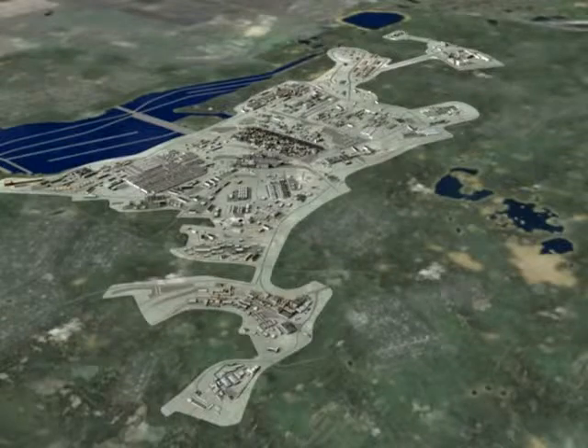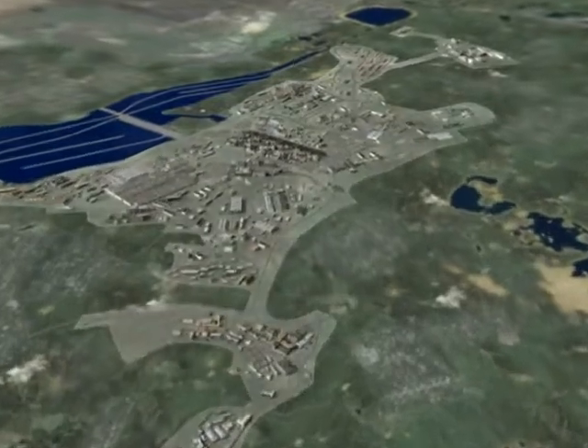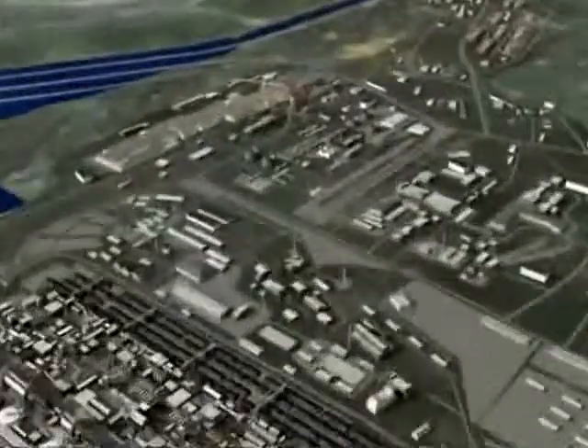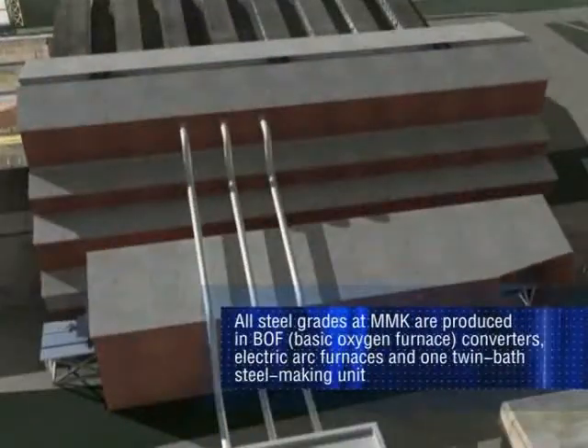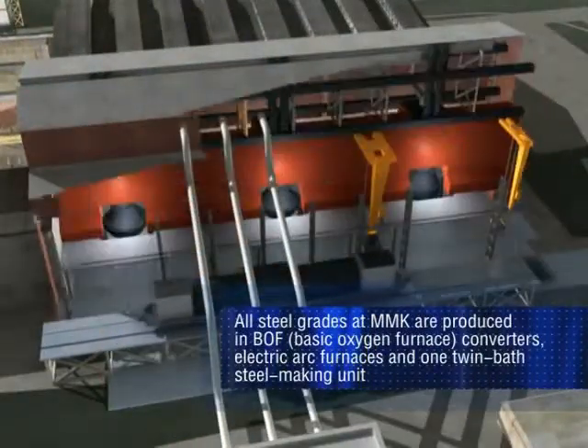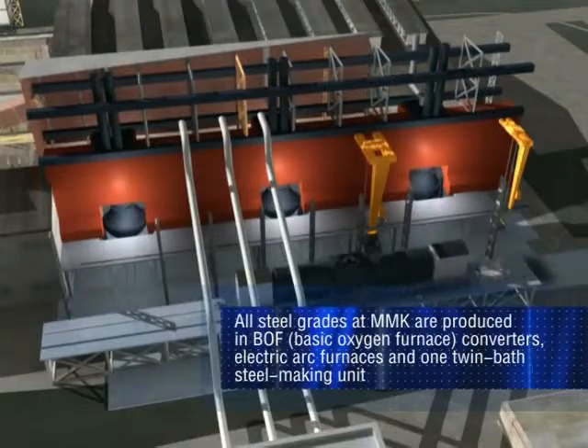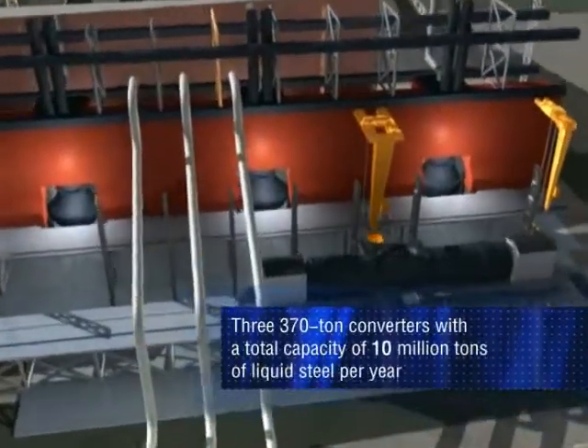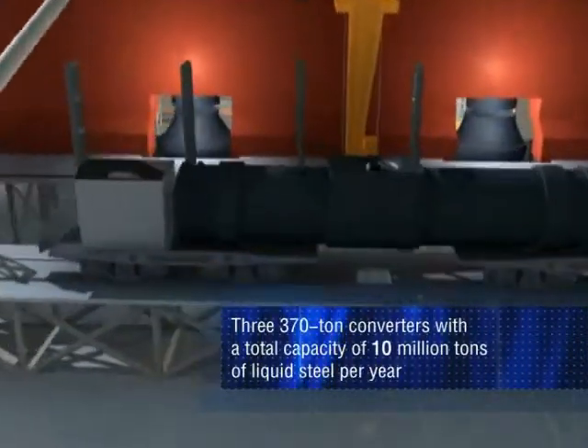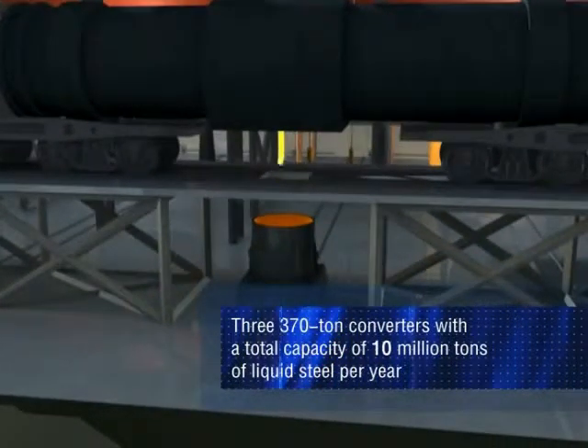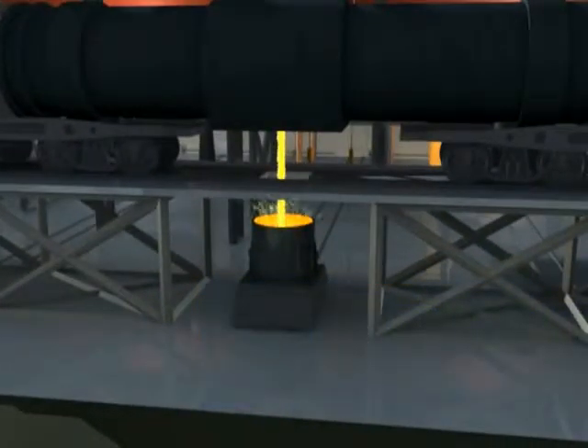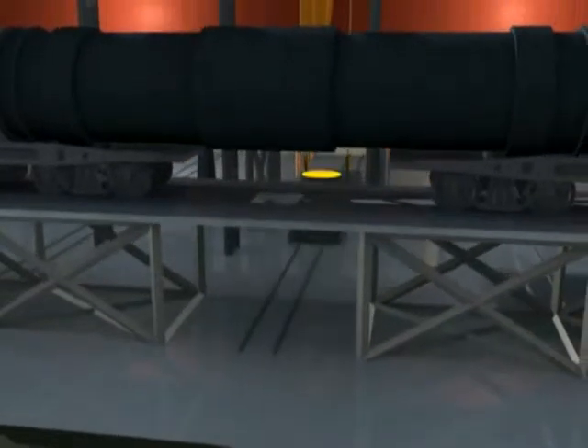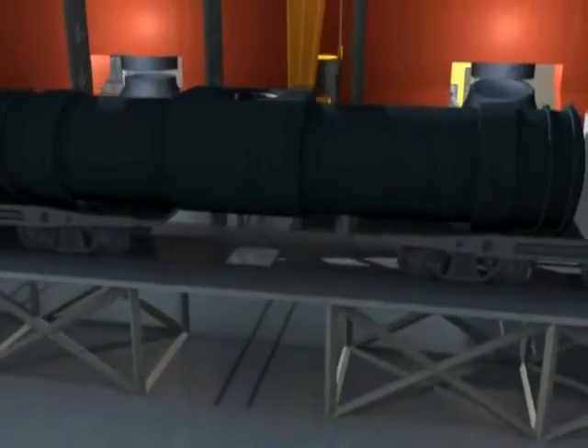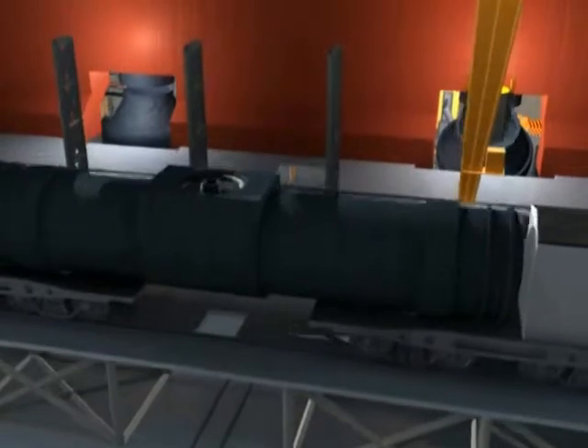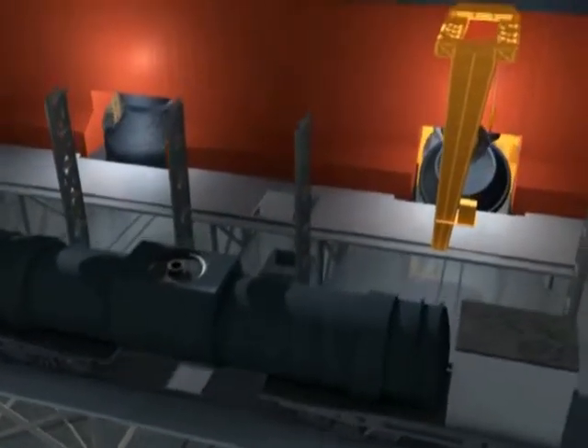All steel grades at MMK are produced in BOF, basic oxygen furnace converters, electric arc furnaces, and 1 twin-bath steelmaking unit. The BOF plant comprises 3 370-ton converters, with a total capacity of 10 million tons of liquid steel per year. Hot metal from the blast furnaces is transported to the BOF plant in torpedo cars. Then it is poured into charging ladles, and from there into the converter.